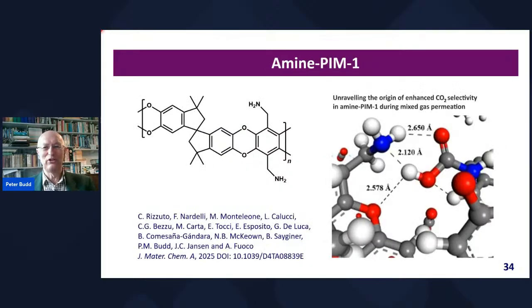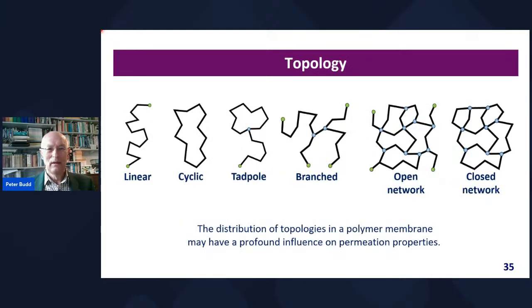I'm only going to mention one briefly, which is an amine modification, which is always interesting because of its ability to interact with carbon dioxide. And it's something we've been looking at over quite a few years, again, in collaboration with John Jansen and colleagues at ITM-CNR in Italy. And recently, they published, it's online as an accepted article in Journal of Materials Chemistry, an attempt to really understand what's going on when carbon dioxide interacts with this sort of polymer. And there's strong evidence that there's an element of chemisorption as well as physisorption going on, which actually leads to some quite interesting behavior and improved selectivity when one's looking at mixed gases as compared to single gases.